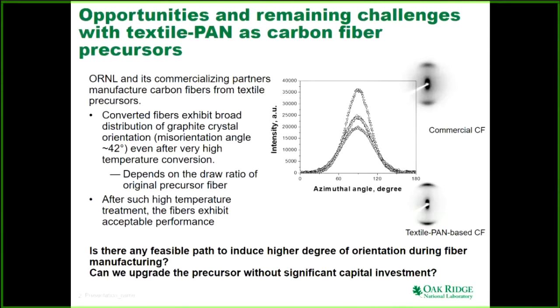Now, the misorientation angle in this case is really very broad for textile-based carbon fiber, and that is a challenge. That's why you see some variation in the carbon fiber properties. The misorientation angle in this case is 42 degrees. Can we reduce that angle and improve the performance? That is our goal, but that would depend on the drawdown ratio of the precursor fiber that we use to make the fiber. I'll come back to this slide again.